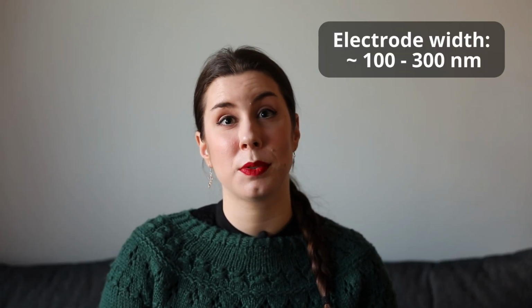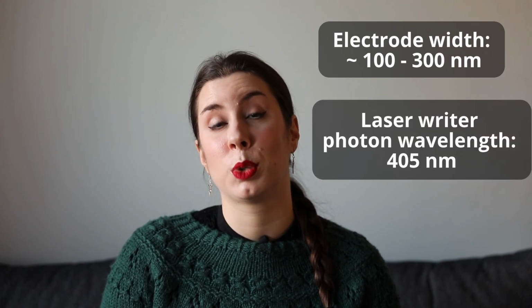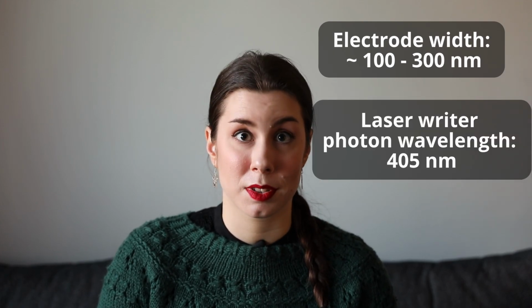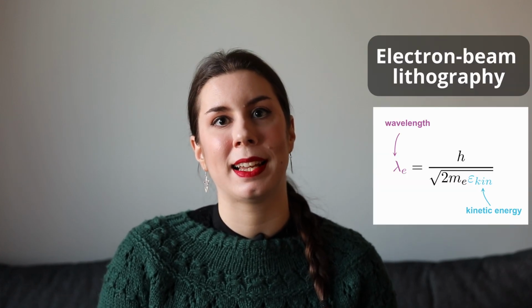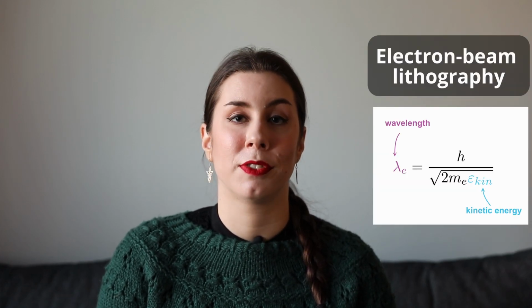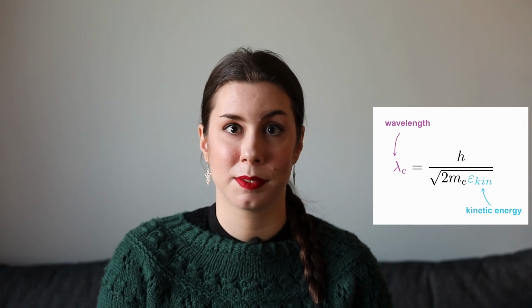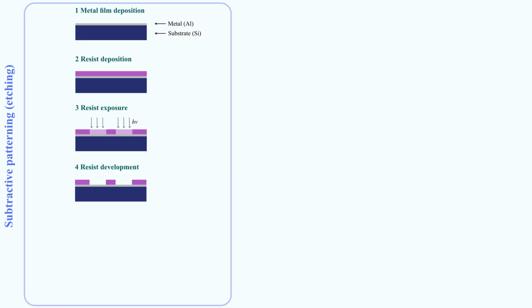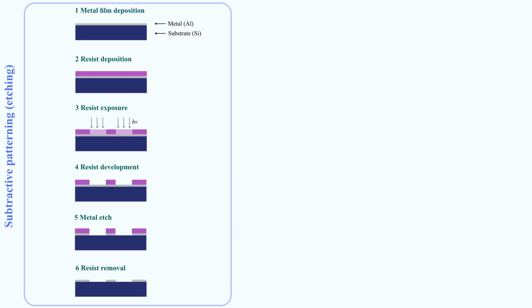First of all, the junction electrodes are super narrow. They're so narrow that we can no longer rely on our laser writer to expose them because the pattern would be smaller than the wavelengths of its photons. Instead, we will resort to electron beam lithography because we can get appropriately narrow wavelengths out of electrons much easier than out of photons. The actual patterning technique is in a sense the opposite of what we did before. Before we took the substrate, deposited a metal on top, then patterned a resist on top of the metal and transferred the pattern into it.